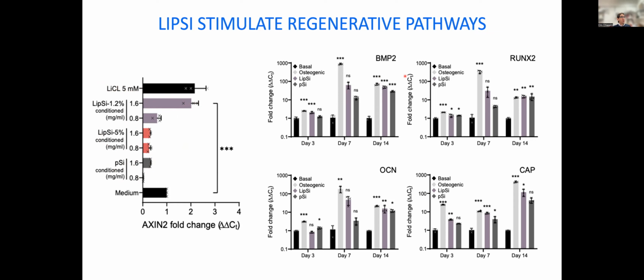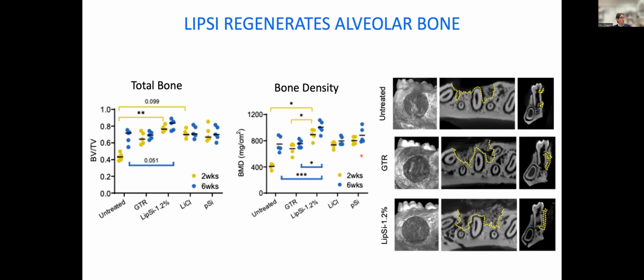Instead, if we look at pathways that stimulate bone growth or a growth of dentin, which is the other side of the mineral tissue on the tooth, we do see that both the porous silicon and the lithiated porous silicon stimulate the generation of mineralized tissue, as we would expect, because the silicon stimulus is strong in that.